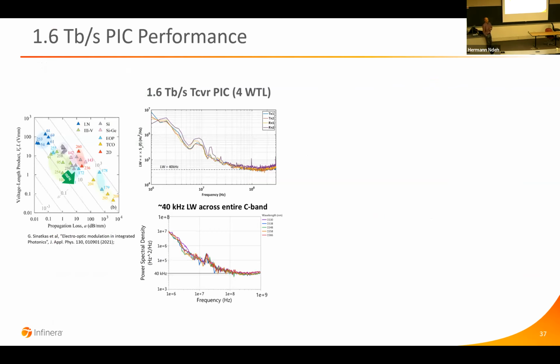And so it talked a little bit about some of the materials innovations, and one of the things they really enabled was the ability to make the lowest loss, highest performing modulators, which is a combination of loss in the modulator and how much voltage it takes to modulate the modulator. And so the devices at Infinera are actually off the chart relative to conventional III-Vs that have been made, having low loss and low voltage modulation. And a lot of that goes back to the materials developments that I talked about earlier.